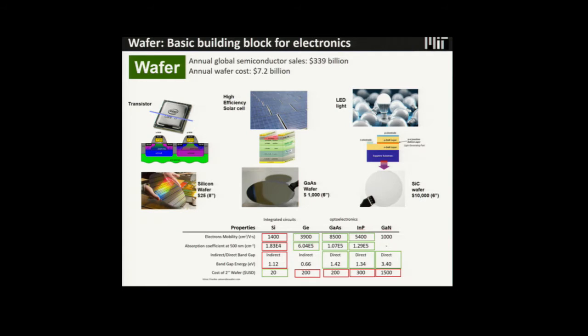And for solar cells, what is the mainstream material? Still silicon, even if we know there are so many other materials that can have much higher efficiency than silicon, but we have been stuck on silicon. For example, a gallium arsenide solar cell's efficiency can go up to 30%. If you stack up III-V materials, you can have 42% efficiency, but we have been stuck on silicon. Why? Because simply a 6-inch gallium arsenide wafer for $1,000 is super expensive. So an assistant professor cannot afford to make a lot of gallium arsenide solar cells.